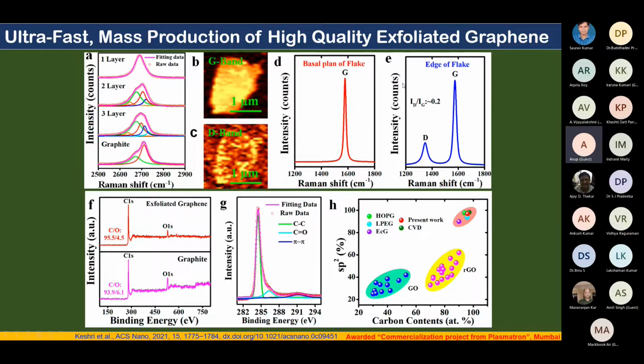impurity. And when we take image E from the edges, you can see that the D peak is coming. So what we can conclude from this analysis is that the edges contain some impurity, with ID by IG equal to 0.2. However, the basal plane does not have any kind of defect.